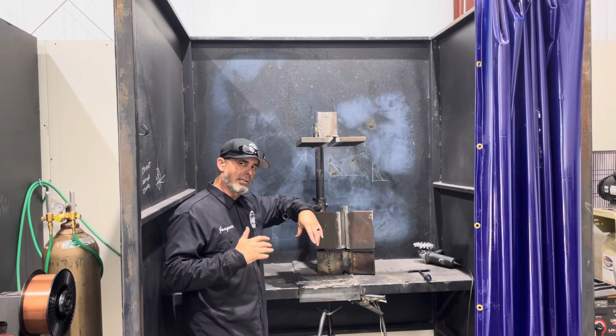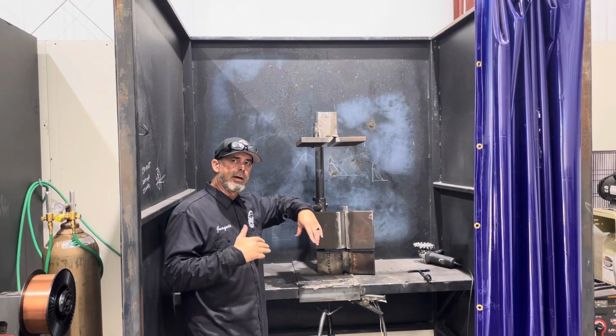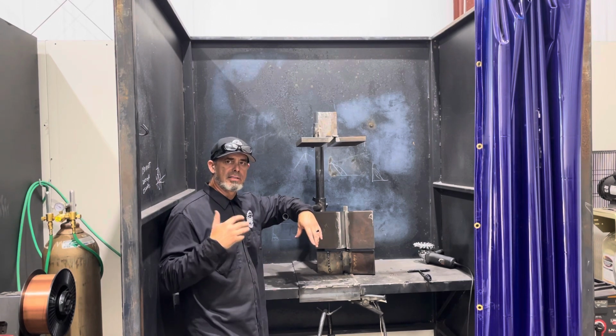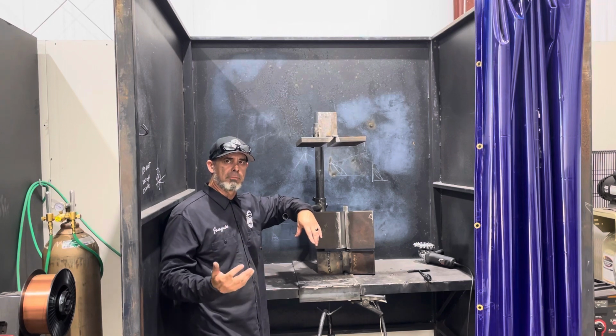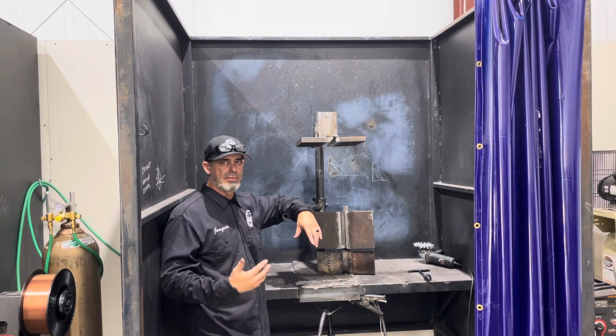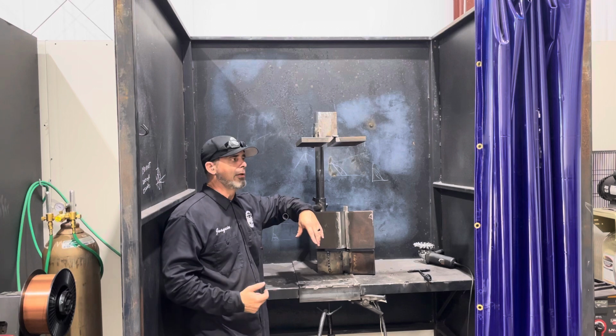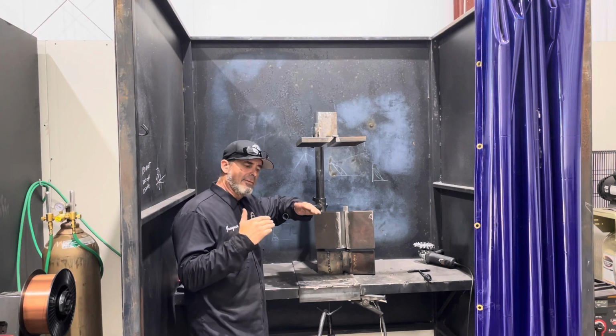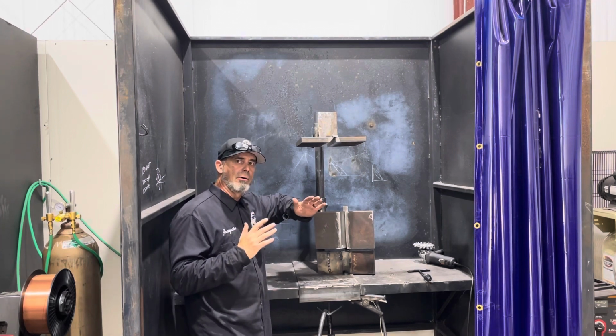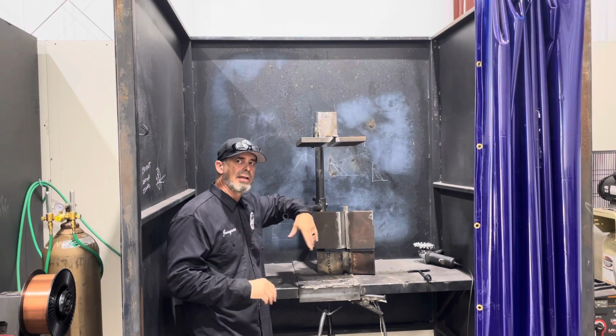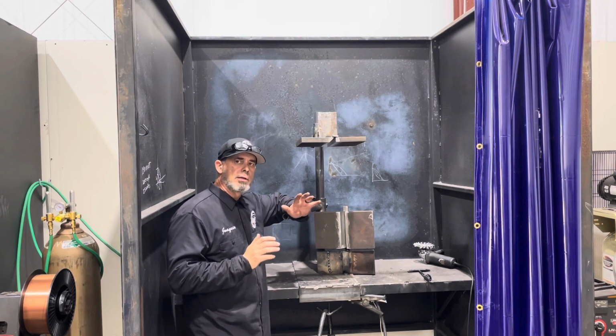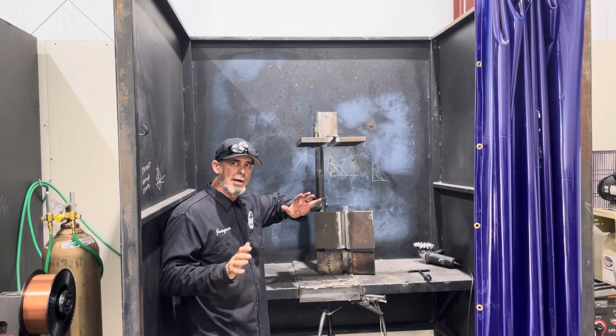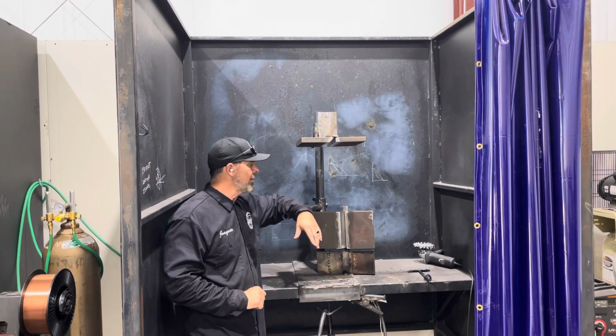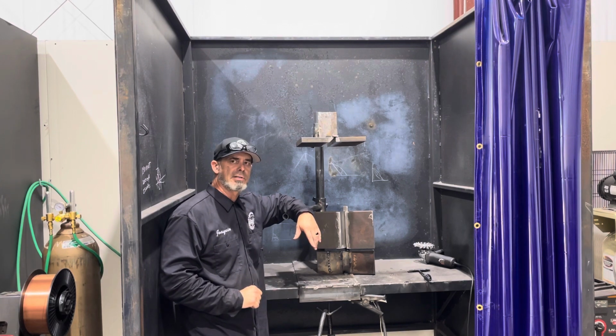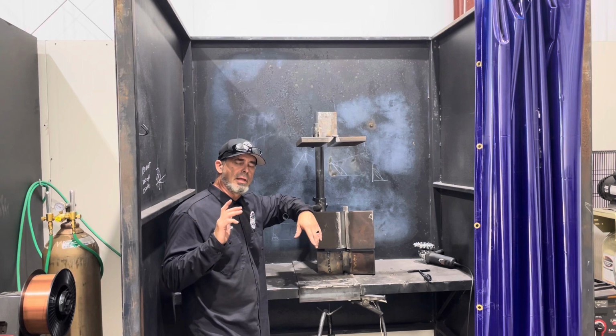So when you look at the D1.1, it specifies that up to 2.5 inch thick steel. Once you get above 2.5 inch thick plate, then it goes up to 450 degrees Fahrenheit for your interpass temperature. So we have a window. Our window that we want to maintain these plates at is 300 to 400 degrees Fahrenheit. So let's stick to it and let's make this a successful test. I'm going to make this video in segments.